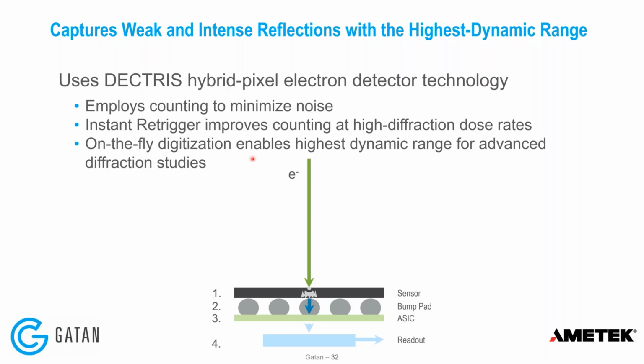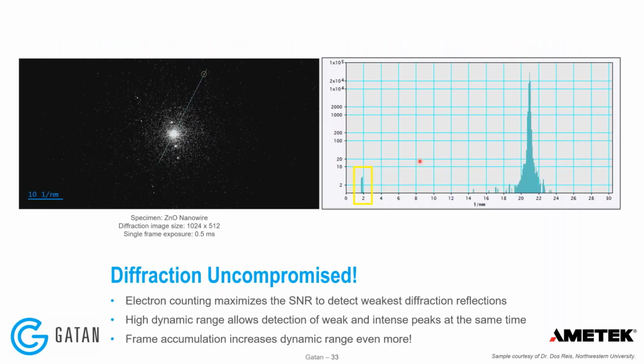And then because of on-the-fly digitization, it also gives you the highest dynamic range, which is another very important quality of the detector that is needed for diffraction imaging, because usually what you have is the dark background of the diffraction and then high intensity diffraction reflections. So you need a high dynamic range detector to be able to collect all of that information without saturating your camera. Here is an example showing the dynamic range of the Stela camera.